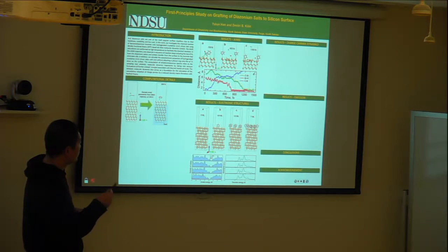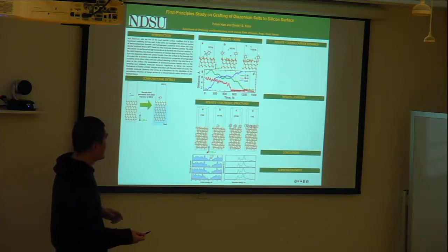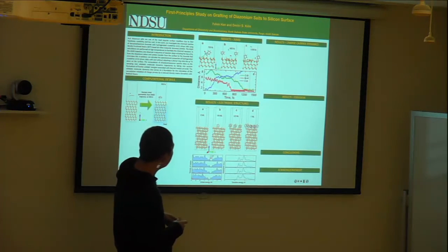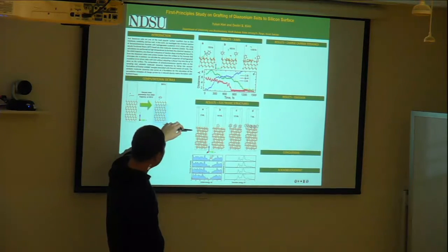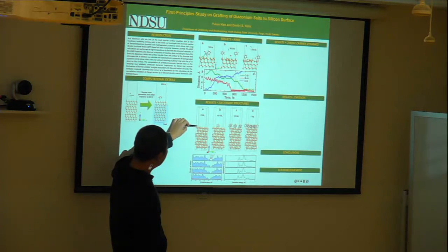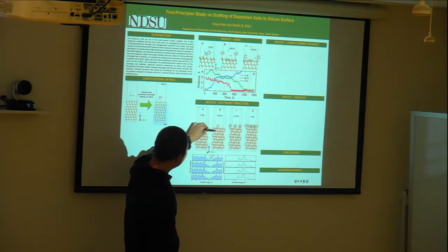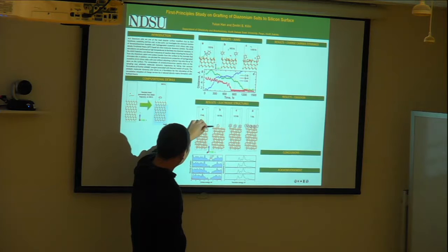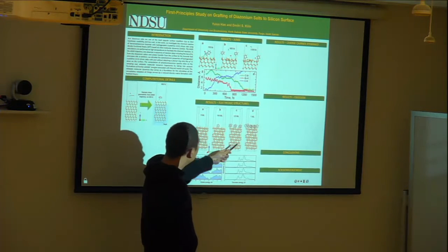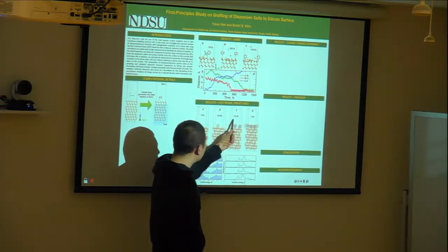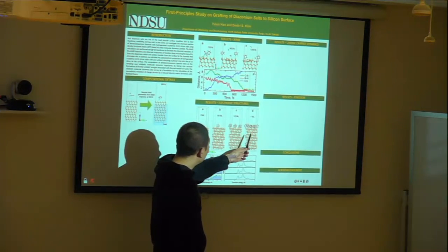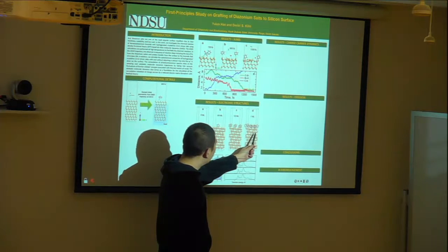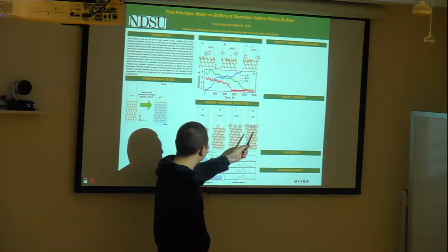So the next step is to quantify the changes due to surface modification. So we prepare 4 atomic models. The first one, the surface is passivated by hydrogen, and in this one, only one phenyl ring is attached to the surface. Here, half of the hydrogen is replaced by phenyl rings, and finally, all the surface is functionalized by phenyl rings.